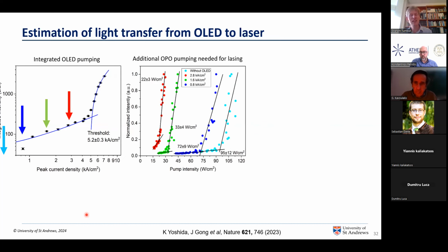But actually, that comes partly because the laser cavity that we had was very much optimized to minimize thresholds, and so we've not got the optimum output coupling on this laser yet. And so I think that's one area where we can do better, and we know that we can get 10-15% slope efficiency out of an optically driven laser.